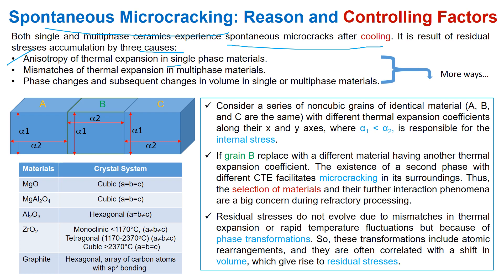That means single-phase, multiphase, or volume change. Non-cubic grains with anisotropic CTE facilitate thermal stress to adjacent grains, where alpha 2 is greater than alpha 1. If another material replaces grain B — non-cubic grains with anisotropy — and we introduce another phase, the additional CTE difference further expedites the micro-cracking in its surroundings. Thus, the influence of the secondary phase is a big concern.